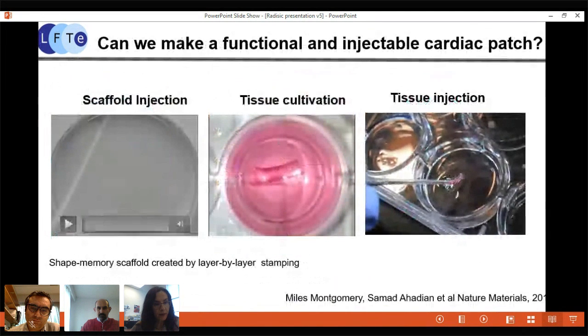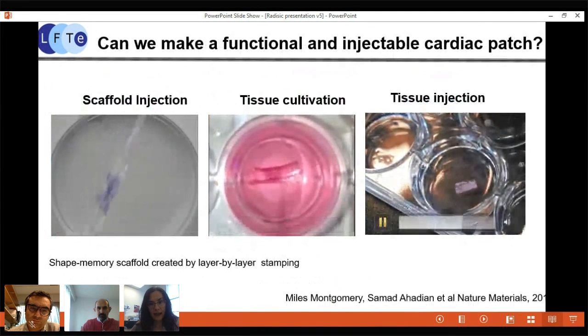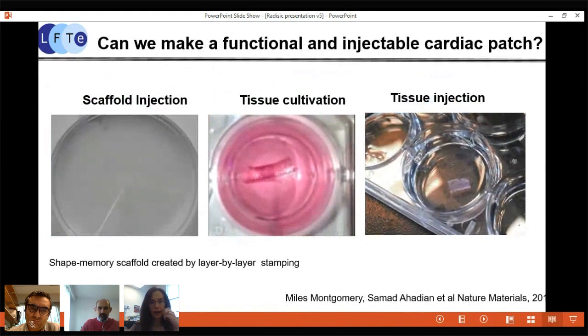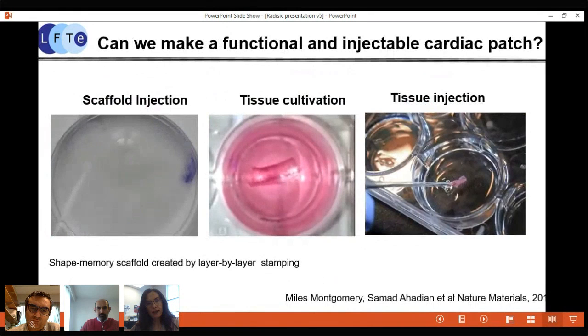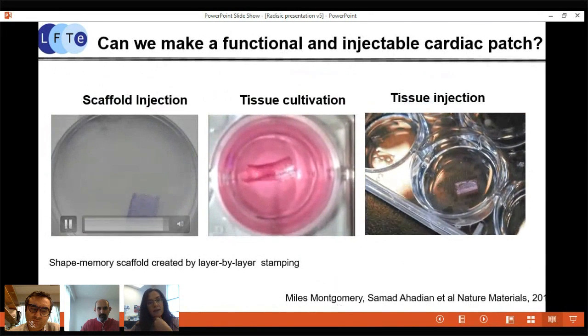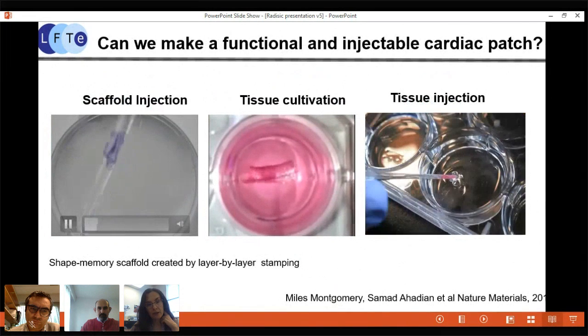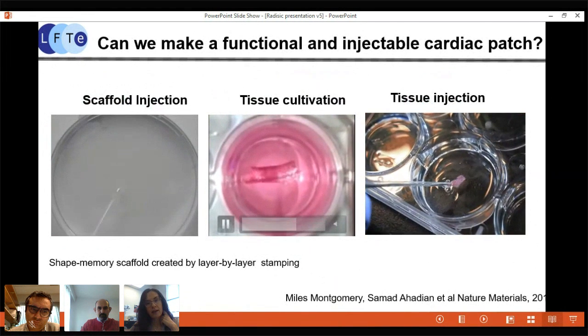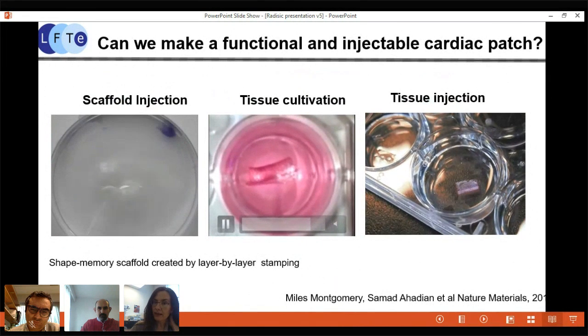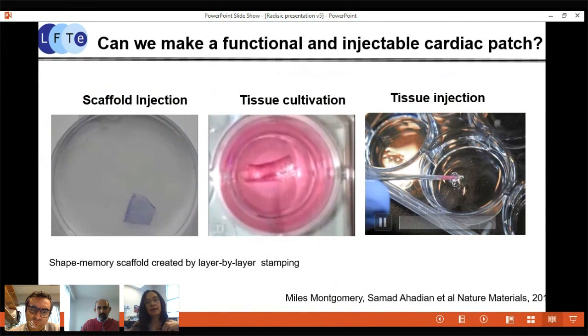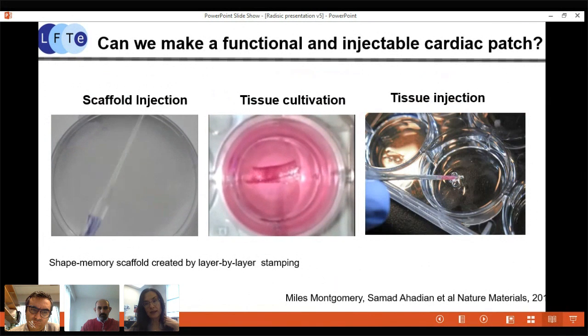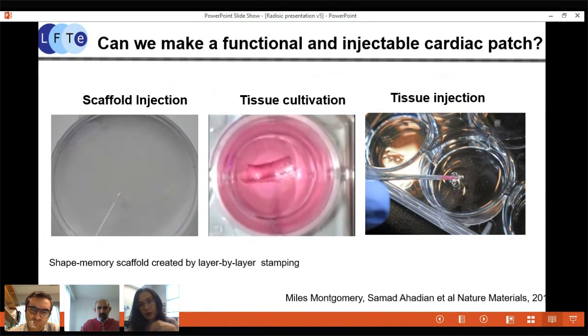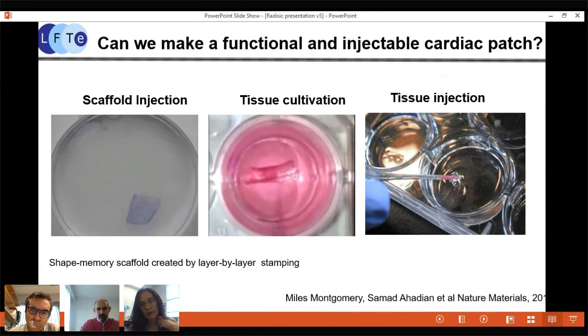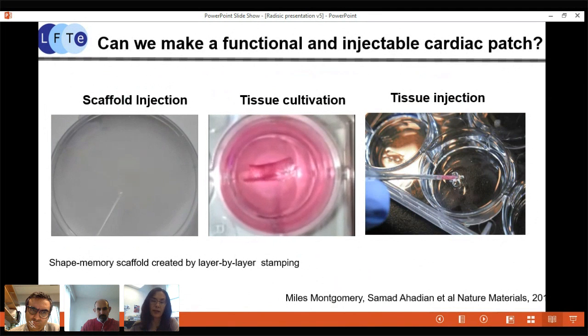And so the shape memory is actually based on the design of the scaffold microstructure. In particular, we can see here that the scaffold can be injected in a PBS bath. It opens up after injection. The scaffold supports beating of the tissue, and it also supports injection of the tissue, as you can see in the last video. Using the P200 pipette, we are able to actually inject this tissue. And the video is just running too slowly, in a 6-well plate.